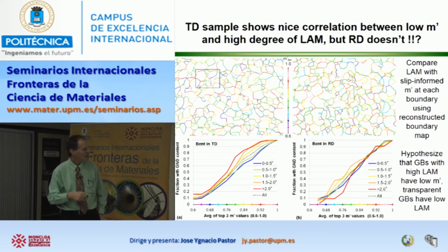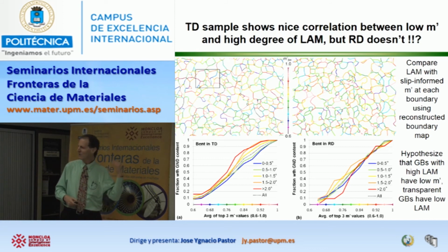And indeed, if I look right here, this is a cumulative distribution of lots and lots of grain boundaries. I see that for boundaries that dislocations pile up at, I have a lower value, and for boundaries where they slip right on through, I have a higher value. And that works great for the transverse direction, but it doesn't work at all for the rolling direction. So much for that theory. It sort of works in some places, but not in others. I have no explanation for this. I don't know why that happens. But it means that this parameter is not enough to explain what's going on.